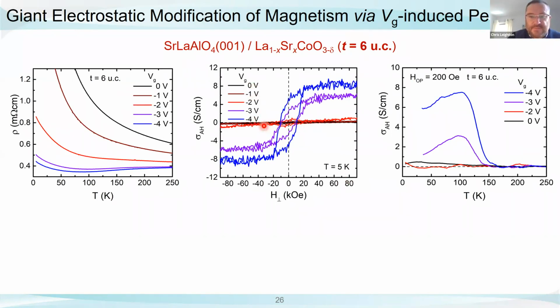And you can see we start from something where there is no anomalous Hall. We progressively turn it on to the point where we end up with a really robust ferromagnet. I want to emphasize it's got a 1 Tesla coercivity, has perpendicular magnetic anisotropy, has remnants. It's about 50% of the saturation magnetization. All these things are important. And I'll point out that we also directly verified this using polarized neutron reflectometry. So if you're not very trusting of the anomalous Hall effect, it was verified to be long-range ordered ferromagnetism.